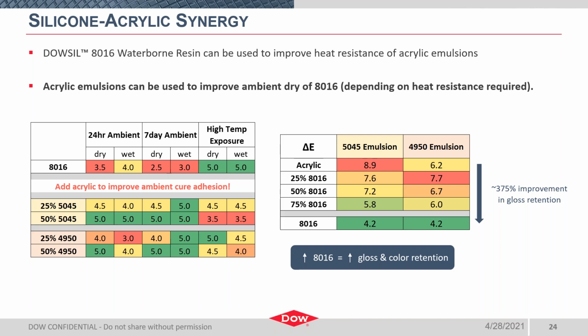The color change for both acrylics as sole binders is poor, but as you move down the table in either column and increase that silicone loading, you improve the color retention, including, of course, the bottom row or the formulation with silicone binder only, showing those best post-heat color retention results. If we consider gloss retention also, as you increase silicone content again, you're moving down in the table, you boost performance. Comparing the acrylic formulation to the pure silicone formulation, we see a huge jump in gloss retention. We are very familiar with this concept, as organic polymers don't tend to hold gloss well when exposed to high temps. They degrade, they burn off, there's nothing left to hold that initial gloss.